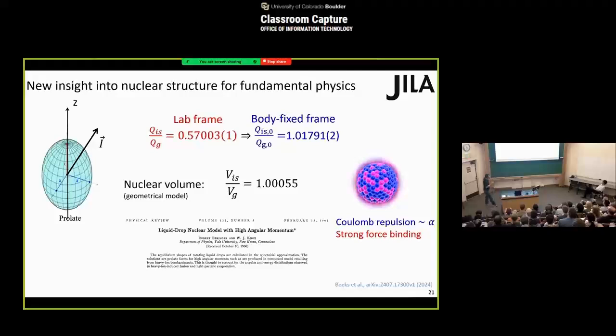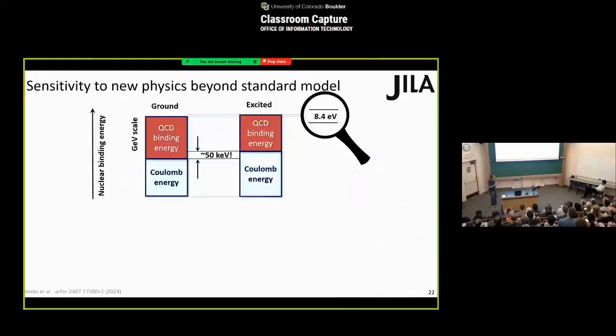So the reason we care a lot about this kind of nuclear structure is because in the nucleus we have this Coulomb repulsion term that is proportional to fundamental constants like the fine structure constant alpha. We also have the strong force binding the nucleons together. So if we look at the nuclear binding energy for the ground and excited state, the change in the Coulomb energy and the QCD binding energy almost cancel each other. This leaves us a very small energy of 8.4 electron volt. That's our nuclear transition energy.